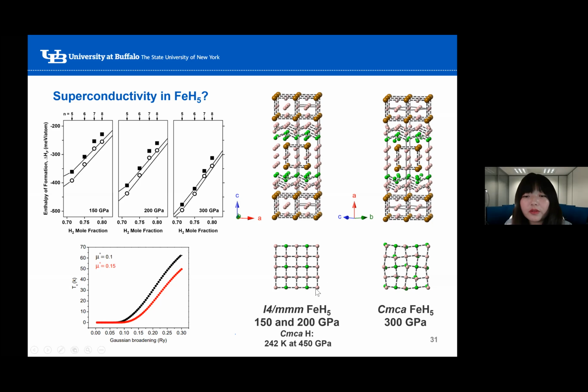The hydrogen network in the I4/mmm phase resembles the Cmca hydrogen phase, which has an estimated Tc of 242 K at 450 GPa. And therefore, we calculated the electron-phonon coupling parameters and estimated Tc for these two phases. We found that if we choose a properly small Gaussian broadening, which is used for the approximation of the double delta function, there's no superconductivity. So that's our conclusion for that part.